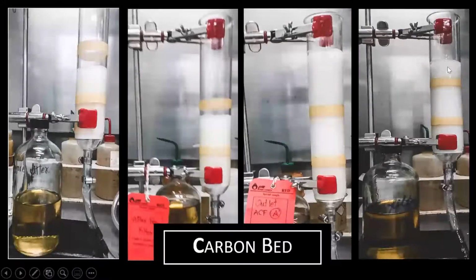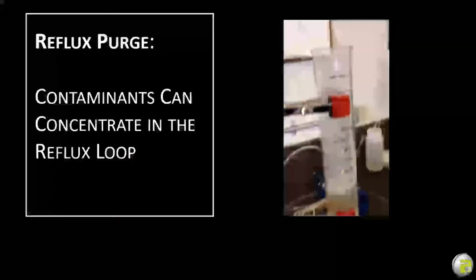And then this is eventually the lean after the post-filter that was feeding the contactor. So because we went through filters, a carbon bed and filters, the amine foamed worse going into the filters than it did coming out. So make sure you're using the correct carbon. Don't use acid wash. Make sure it's a reputable vendor. Carbon can cause you grief.